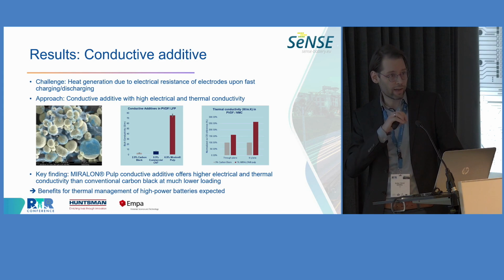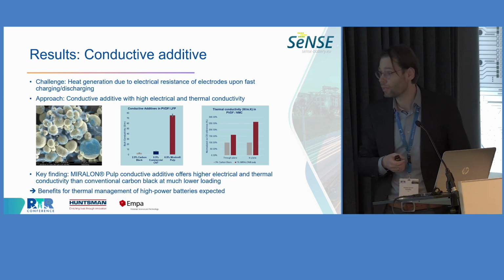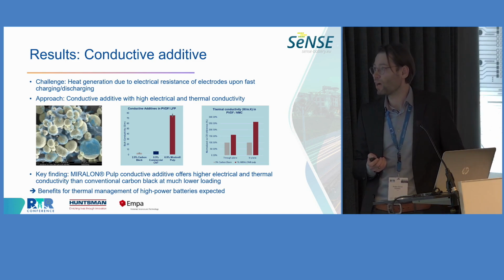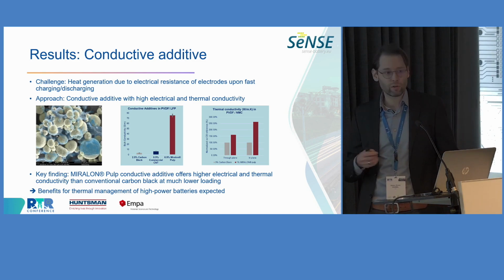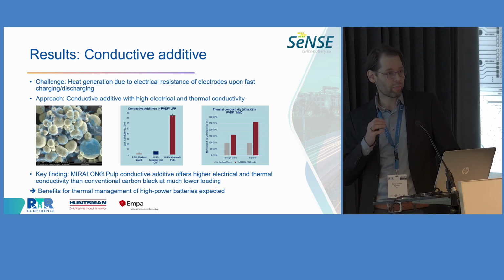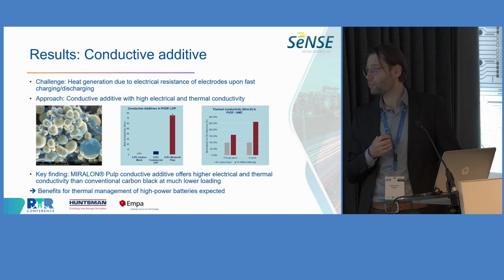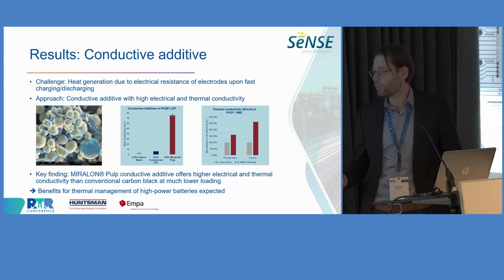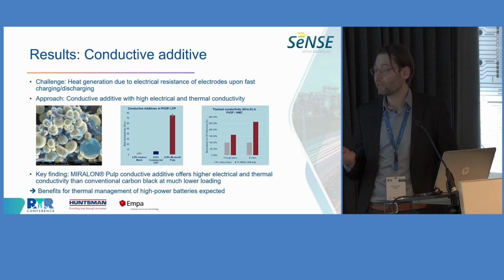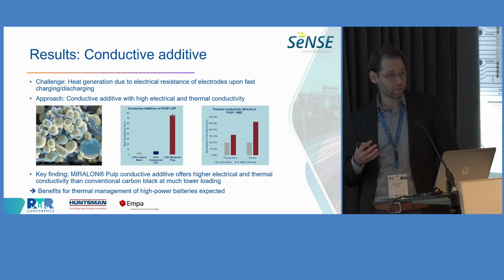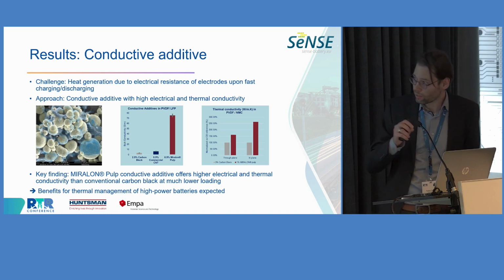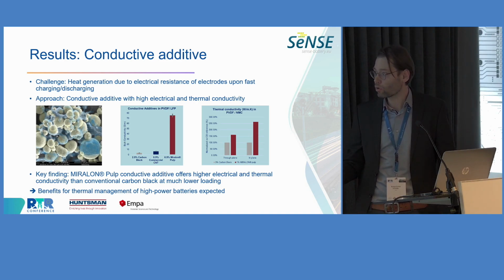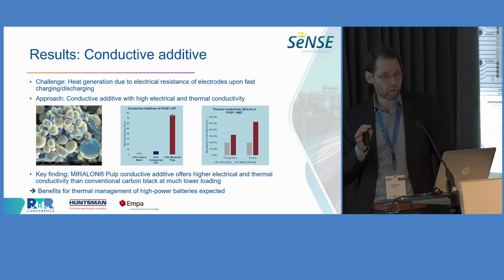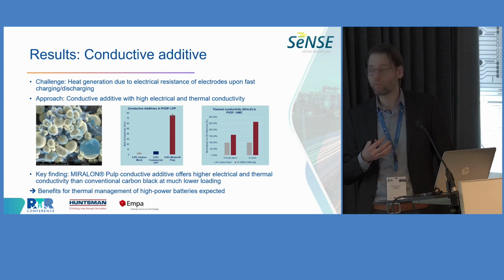And the larger the cell, the higher the inner temperature that is reached inside the cell. And our approach here is to reduce the electrical resistance of the electrodes, because that's a major contributor to the heat generation inside the cell. And here we are working with the company Huntsman that has a very nice material called Miralon pulp that is an alternative conductive additive for electrodes. And when we add this additive in rather low quantities to the electrodes, around 0.5 to 1% of this material, we can significantly improve the electrical as well as thermal conductivity of the electrodes.